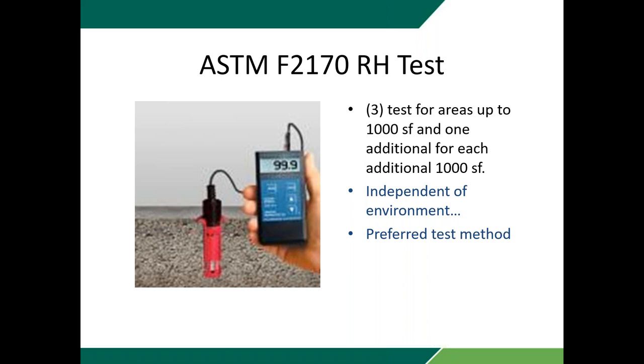But the relative humidity test is done in which they actually drill a hole into the concrete to a particular depth based on whether there's a vapor barrier or not and these kinds of things. They drill a hole in the concrete, they let that sit and acclimate, and then they put probes in and they measure the relative humidity in the concrete slab itself. And the reason why this test is so good is, one, it's independent of the environment.